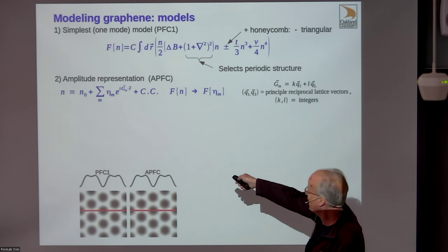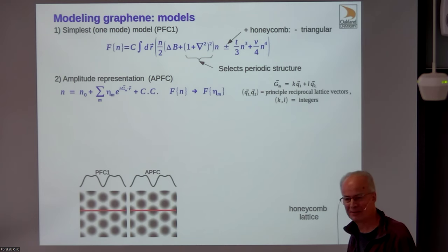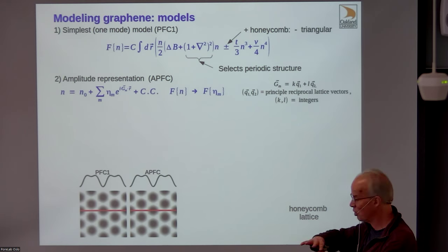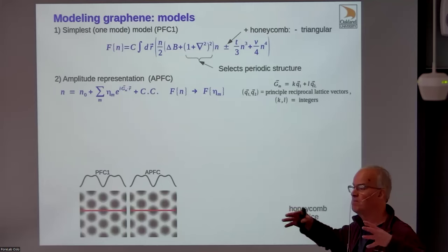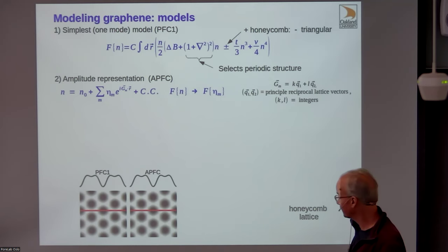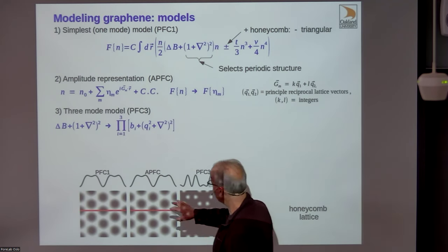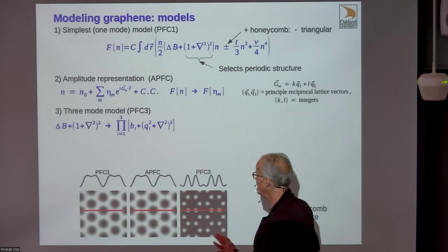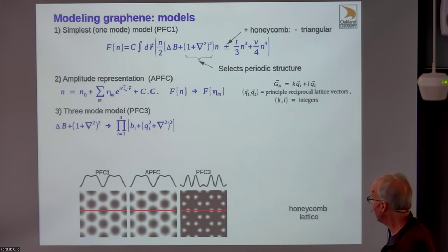Another way to model this is to model the complex amplitudes rather than the density directly. This is what Nigel Goldenfeld and collaborators at UIUC did. The advantage is that the amplitudes are nearly constant when there aren't too many distortions, so your grid spacing can be much larger, allowing drastically bigger systems—simulations equivalent to about 10 to 100 billion particles. You can also design more complicated models that allow you to tune the Poisson ratio and other properties to better match experiment.